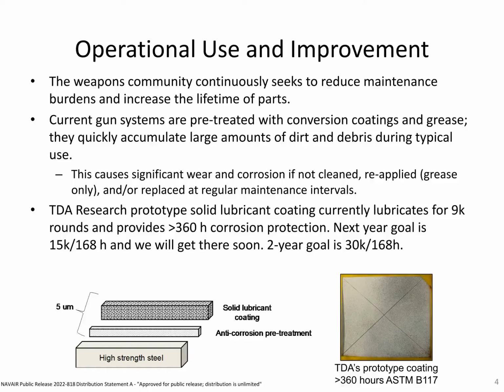The prototype coating is shown on the bottom right. This is a standard panel that we coat. It's a flat steel panel with the coating over it. We etch an X into it. It gets down to basically the bare metal, and you put it in the salt fog chamber, and the hope is that the protective coating will keep that X from expanding, which would happen as the metal is degrading and there's rust.